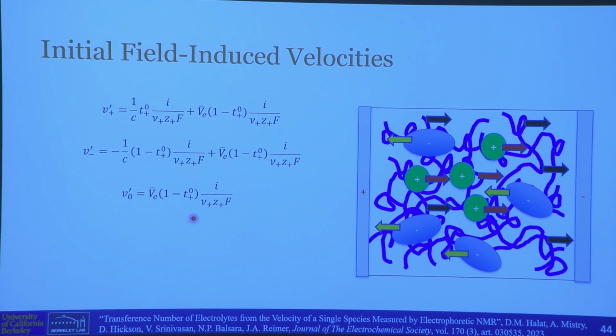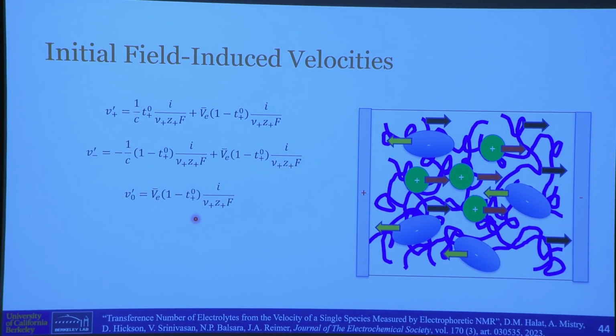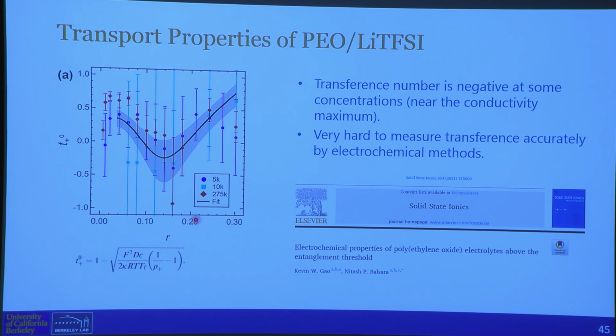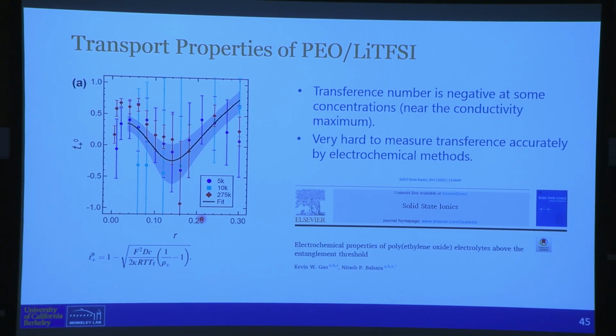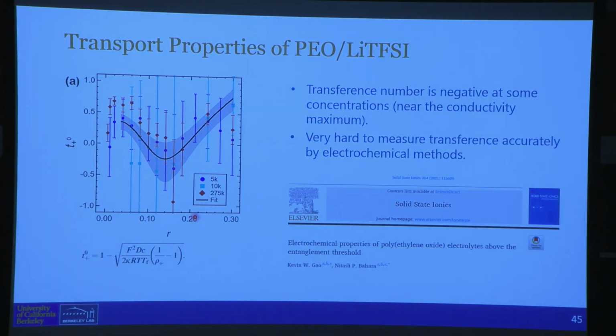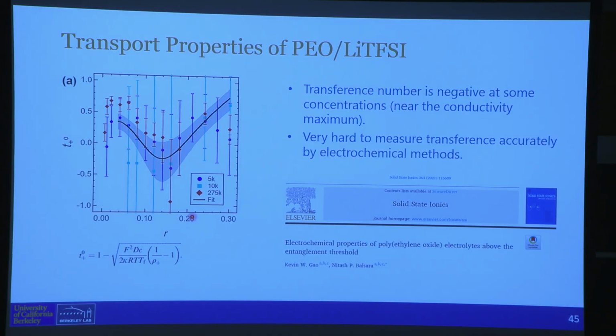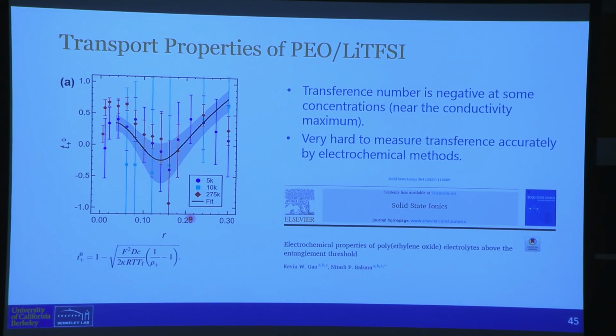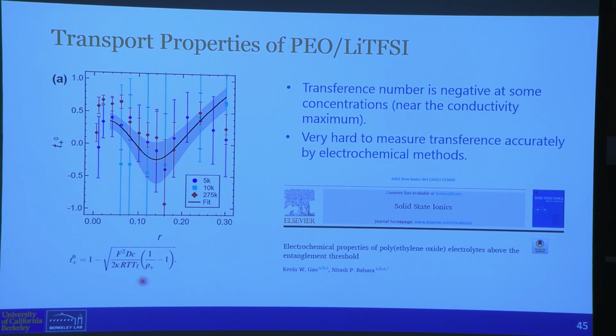number, t plus 0. So there was a conventional way to measure it, and we took as many pains as we could, measuring this quantity the way that Newman taught us, which is that you have to measure the diffusion coefficient and the thermodynamic factor and all this stuff. And at the end, you get this quantity t plus 0. And we did it for different polymers reported in this paper.